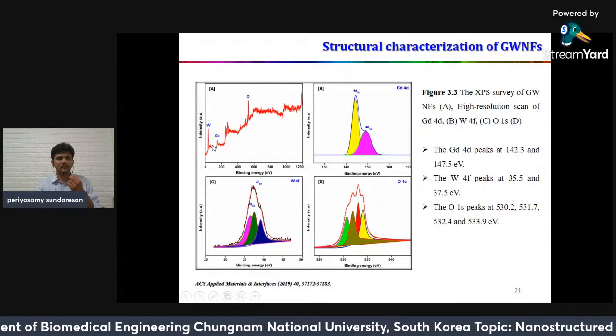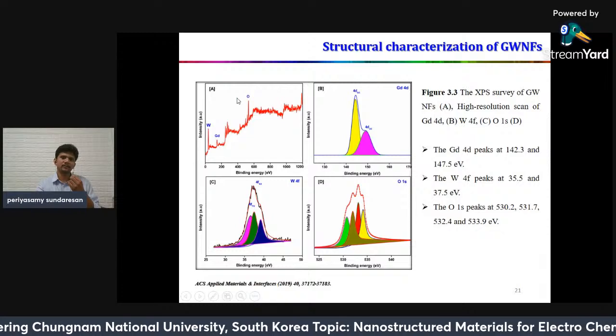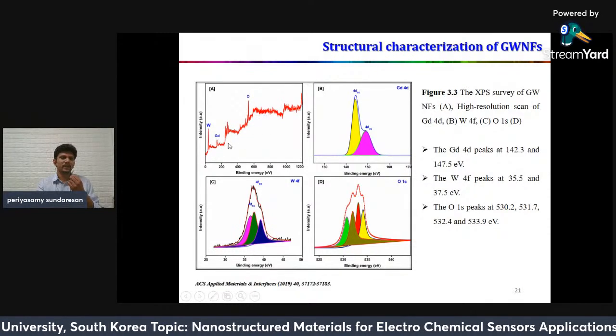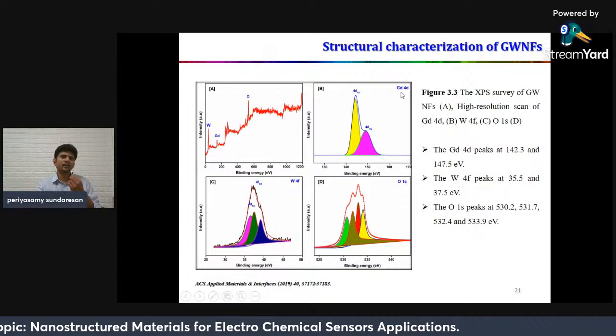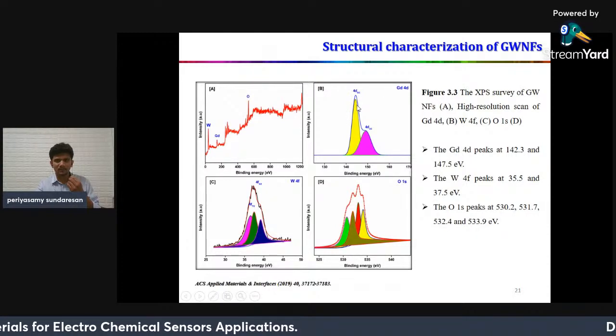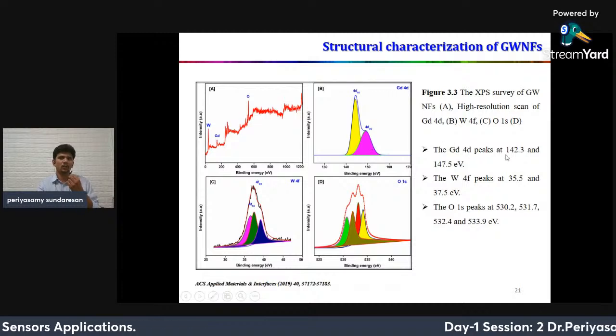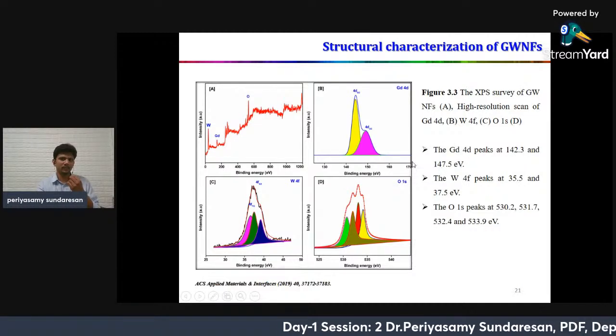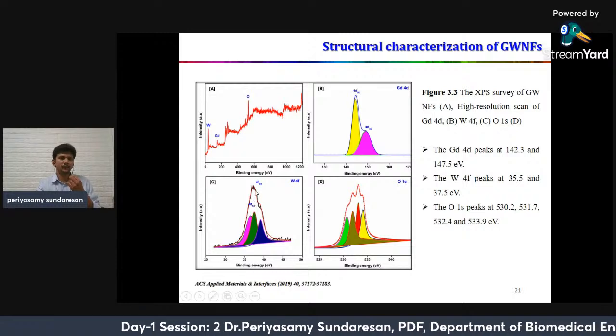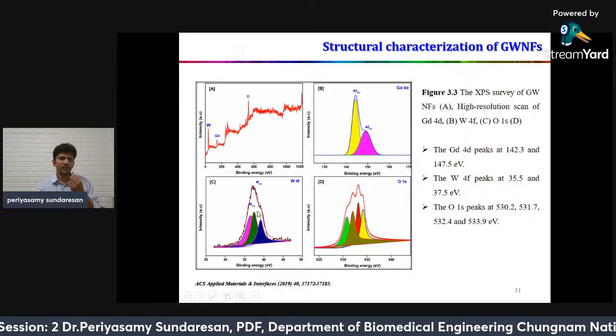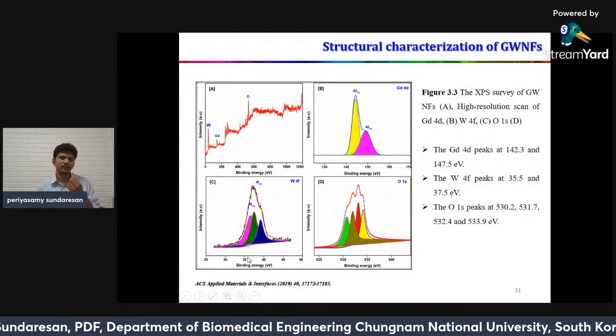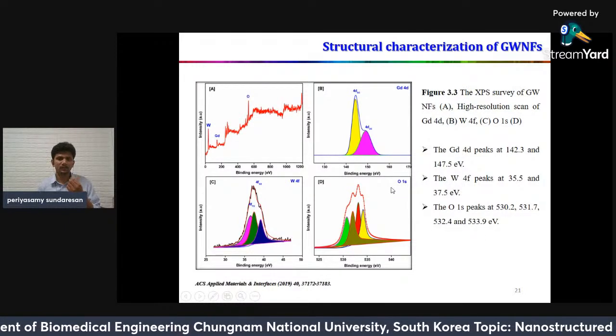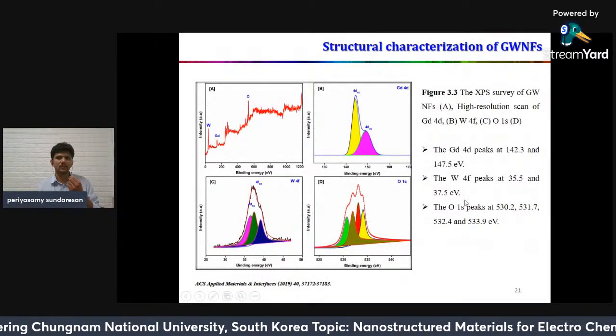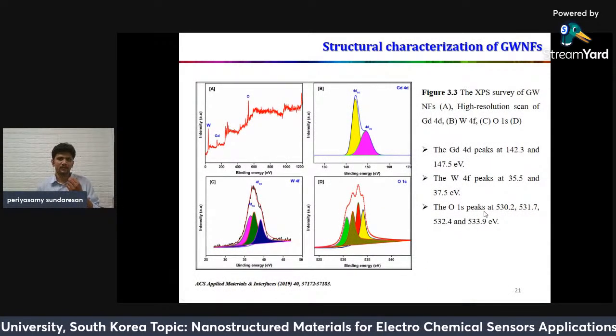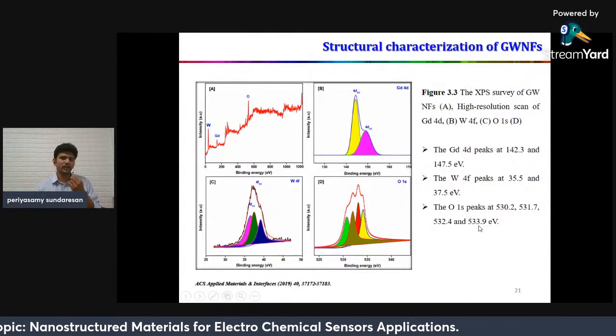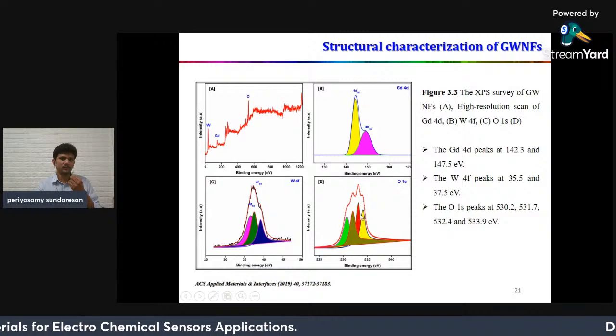So here I get three peaks: tungsten, gadolinium, and oxygen. So they don't have any other impurities. The gadolinium groups are deconvoluted into 4d 5/2 and 4d 3/2 at 142.3 and 147.5, and the tungsten groups are deconvoluted into 4f 5/2 and 4f 3/2 peaks at 35.5 and 37.5. Similarly, the oxygen group is also deconvoluted into 530.2, 531.7, 532.4 and 533.9, which confirms the presence of the oxygen group.